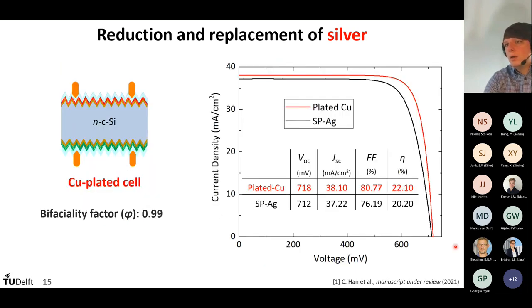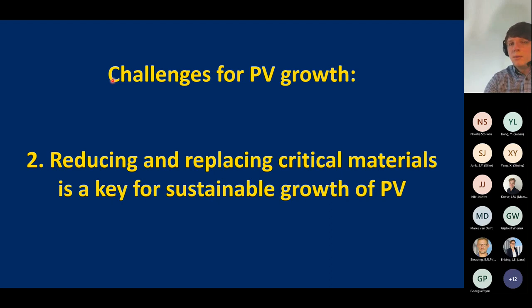So we are also working on this in Delft, and my colleagues made a copper-plated solar cell, which is bifacial. So it has the same efficiency from the rear side as for the front side, which is another thing that increases yield and reduces metal use, and it has 22% efficiency. So it can have comparable efficiency levels to silver. And the main thing in the next couple of years is to scale up copper plating. So this is my second key takeaway. We need to reduce and replace critical materials, which for crystalline silicon PV are silver and silicon today. And if silicon heterojunction cells enter the market, also indium will become critical.